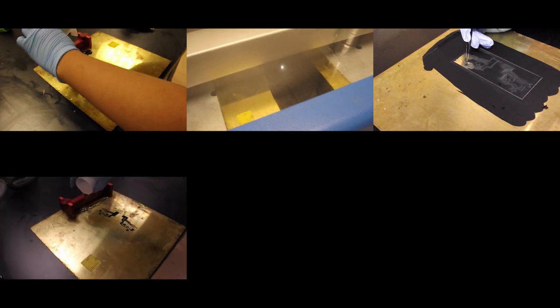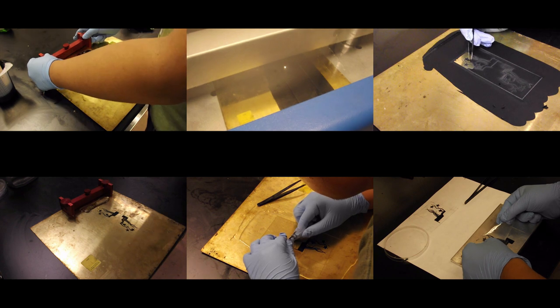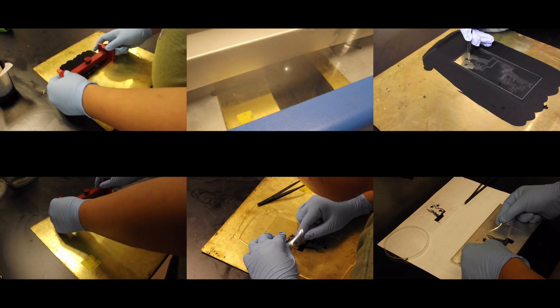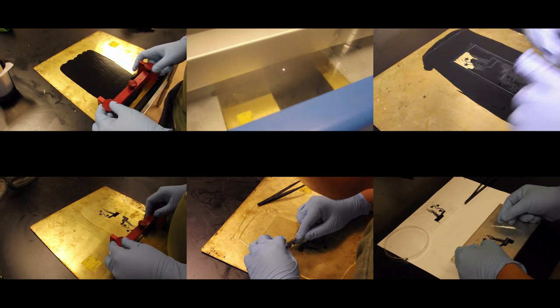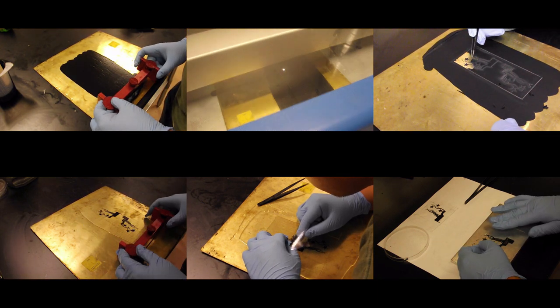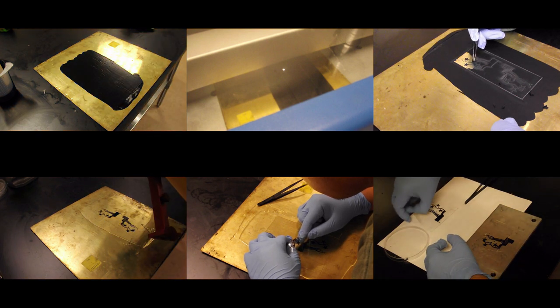iSkin builds on recent advances in material science. The sensor is a sandwich composed of multiple layers of silicone. Non-conductive parts are made of transparent PDMS, while conductors are realized with carbon-doped PDMS. Both materials are biocompatible, flexible, and stretchable. The thickness of the sensor surface is between 0.3 and 0.7 millimeters.